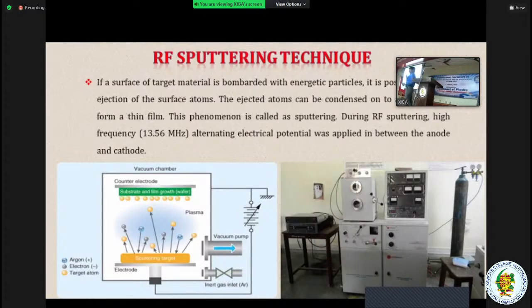For making the TCO, if you want a CdO-based TCO material, we have to use the sputtering technique, the sputtering method. In the sputtering method, we have a target of either cadmium oxide or n-doped cadmium oxide. When you bombard the target with argon ions, the bombarded material will go to the substrate. The substrate is placed at the top, and then the layer formation occurs on the substrate. So this is the equipment used for making the thin film of cadmium oxide.